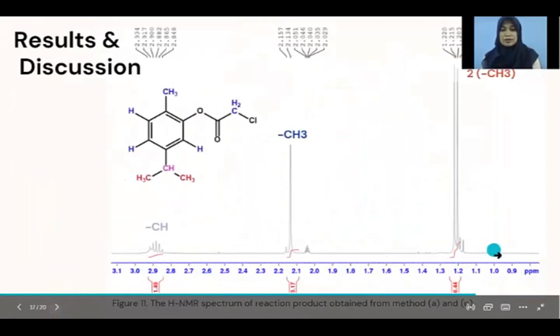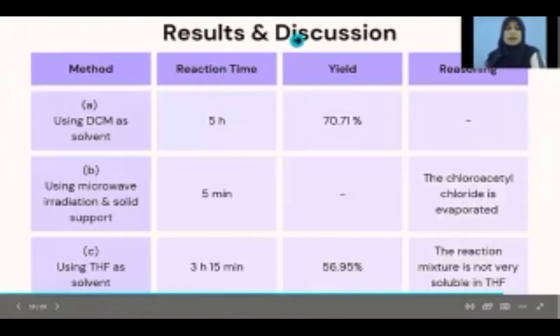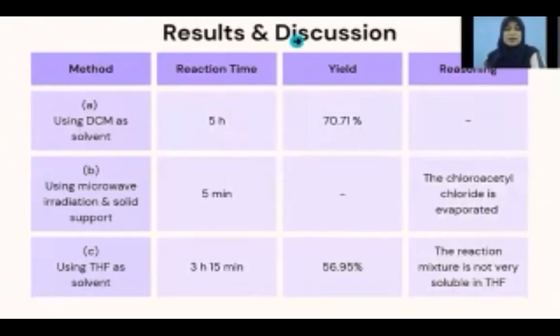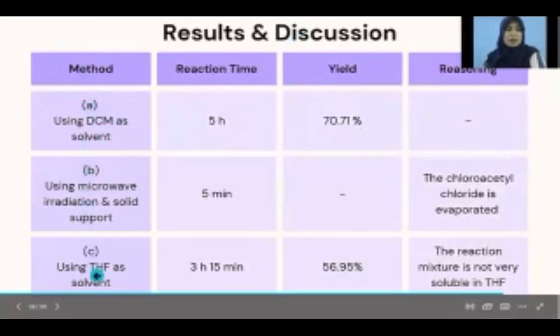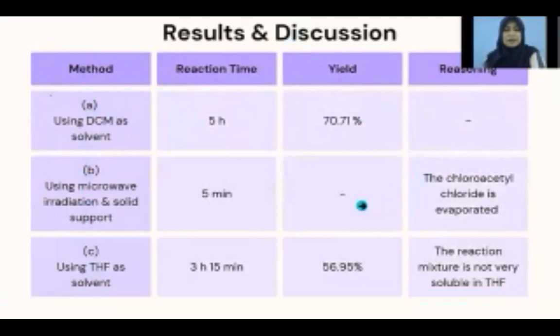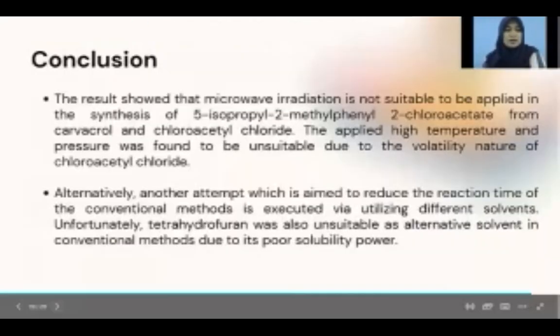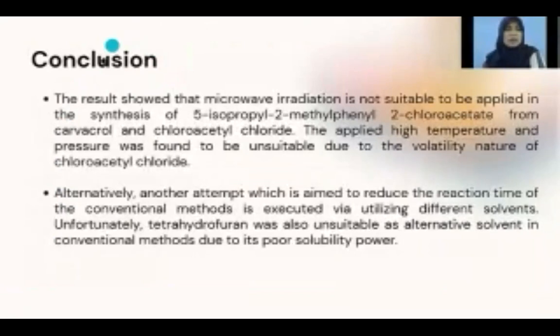And the fourth signal at chemical shift around 1 to 3 ppm confirms the aliphatic protons in carvacryl ester. This table shows the comparison of reactions for synthesizing carvacryl ester by using method A, method B, and method C. Based on the table, we can see that the good result is still obtained from method A by using dichloromethane as a solvent. Then these are our conclusions.